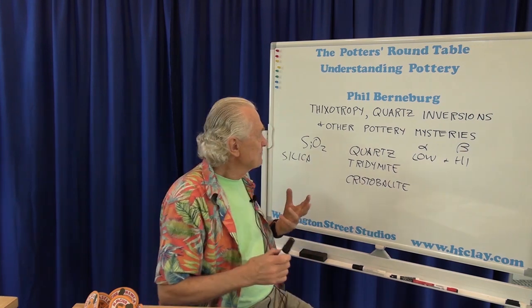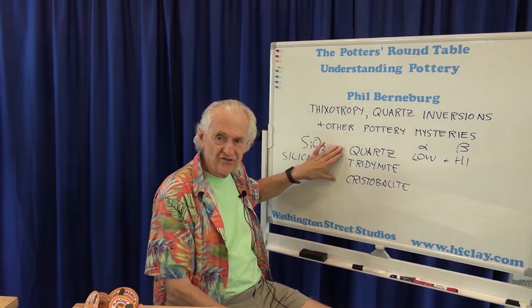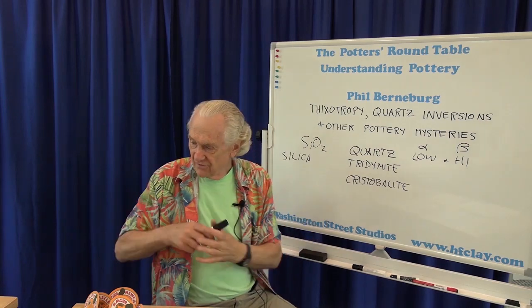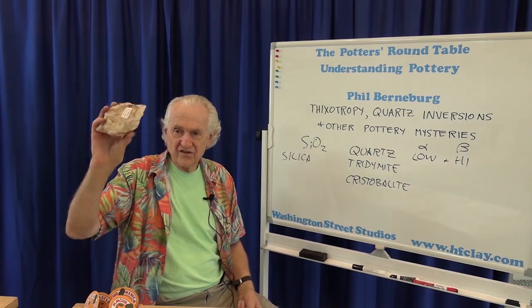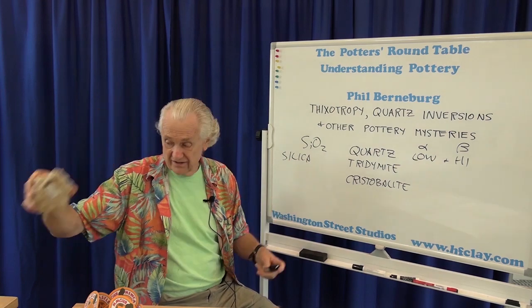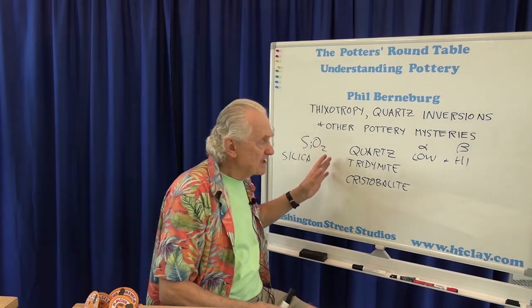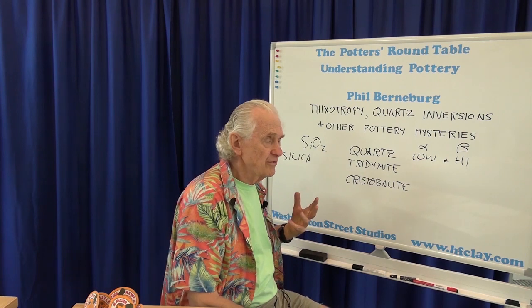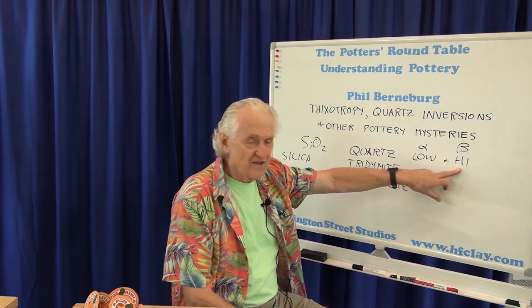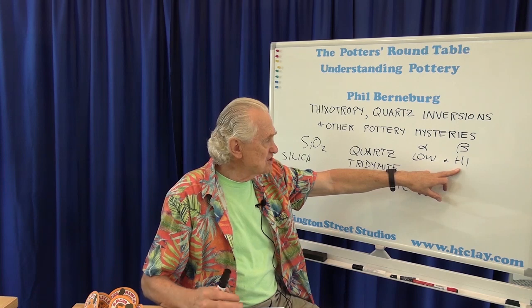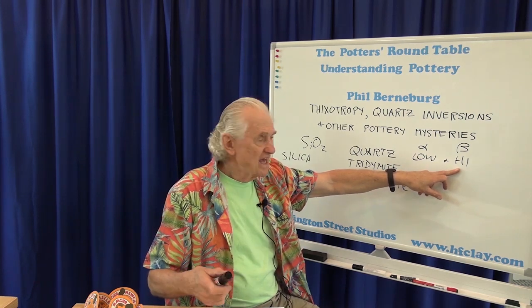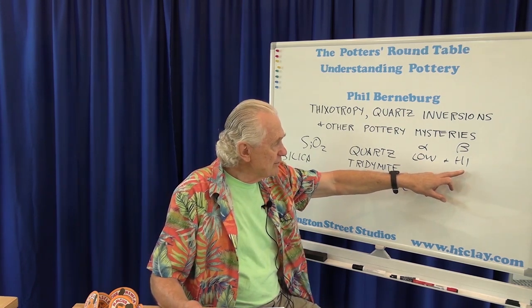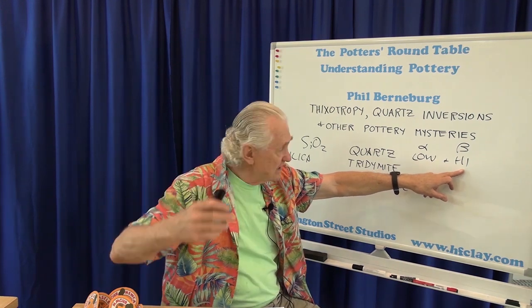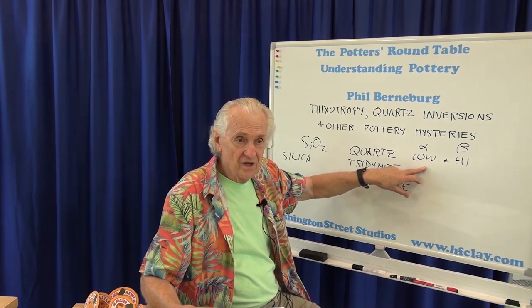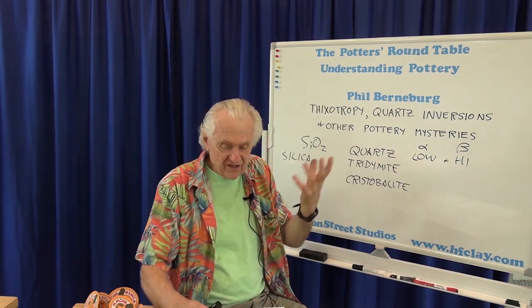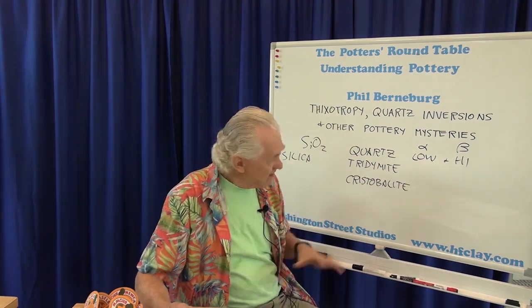And the point is that if you were to take quartz and heat it up, and normally the quartz I'd find in the ground would all be low quartz. Low, again, is relative. But if I were to heat it up to high temperatures, like in a glaze firing, it would actually change to the high temperature form. The change happens around 573 degrees, and then when I cooled it back down, when it got to 573 degrees again, it would change back to the low form. When you were done, there wouldn't be any obvious difference to look at. But all of them do that.